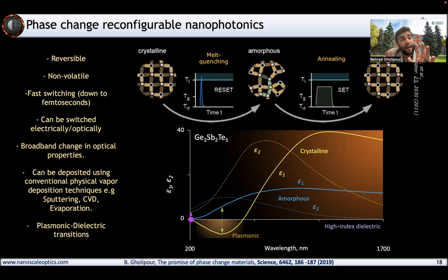And you can see that this is a material that changes between being a metal and a glass in the visible part of the spectrum. That's a very, very interesting property that no other material system exhibits, switching between a metal and a glass in a non-volatile way, and in the telecom band, it switches between a high index dielectric to a much higher index dielectric, if you will, as well.